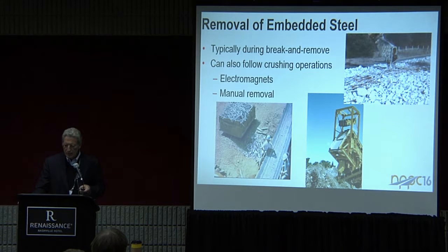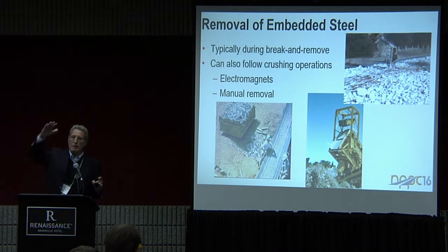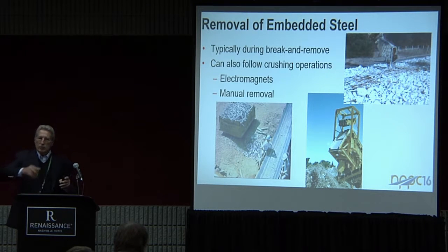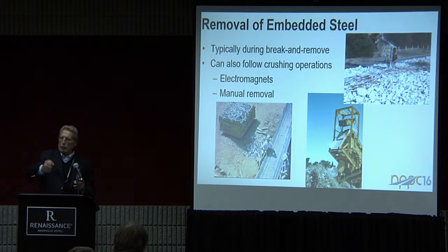If you have steel that's needing to be removed, particularly if you got continuously reinforced, a lot of steel there, that's often best broken up in the field there. Get guys out there with the cutting torches and the pneumatic shears, cut that and remove as much as you can. Whatever doesn't get removed can be removed after it drops out the bottom of the crusher. Really the only modification to the crusher in that case is to drop your belt down a couple feet, so that any rebar that comes through can turn the corner without poking a hole in your belt coming out of the crusher. That kind of ruins your day.